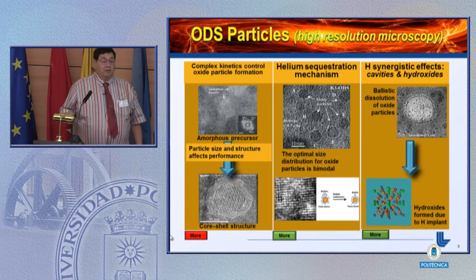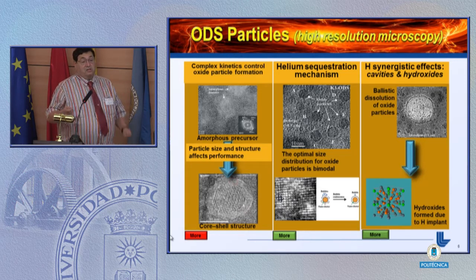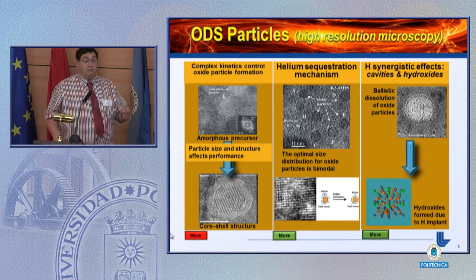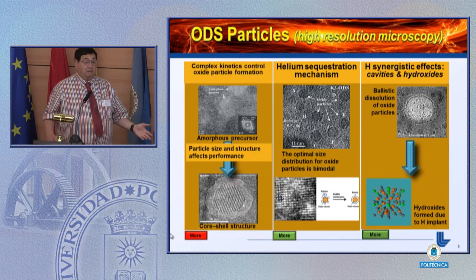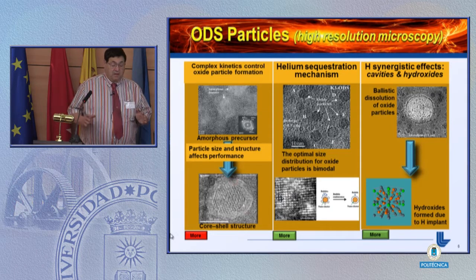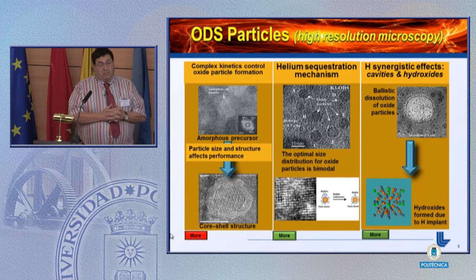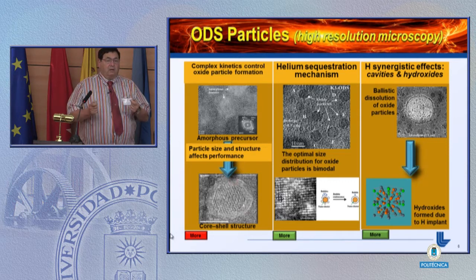Well, the Japanese actually showed that although they got an order of magnitude increased swelling in this synergistic triple beam experiment, indeed, when they analyzed for the hydrogen in the specimen, there was none there. So one of the lessons that one has to learn is that when you're thinking about a reactive species like hydrogen, unlike helium, which is not a reactive species, the effects that you can get aren't necessarily going to correlate with the amount of hydrogen that was in the material after the experiment was done. The hydrogen can catalyze processes in the series of rate equations that describe the system. Hydrogen can affect those and act as a catalyst for, in this case, cavity growth.